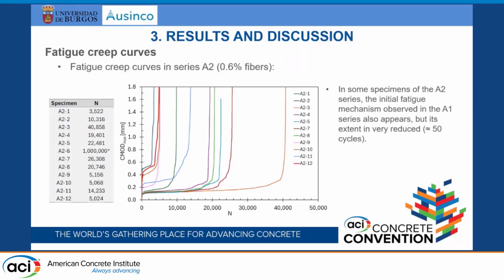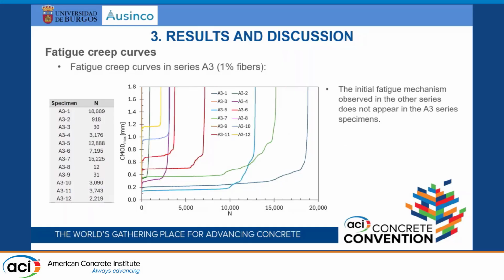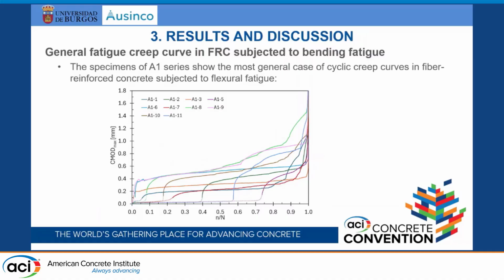If we move on to the A2 series with more fibers, 0.6% of fibers, we see that there is no preliminary region of uncracked fatigue. We are not able to see that. Actually, there is a very, very short part of this previous region, less than 50 cycles, so that's why we can see it here. And if we later see the fatigue creep curves of the A3 series with 1% of fibers, there is no previous section of fatigue. So what we saw is that there is a general case of the fatigue creep curves in fiber reinforced concrete, and this is shown in the A1 series.